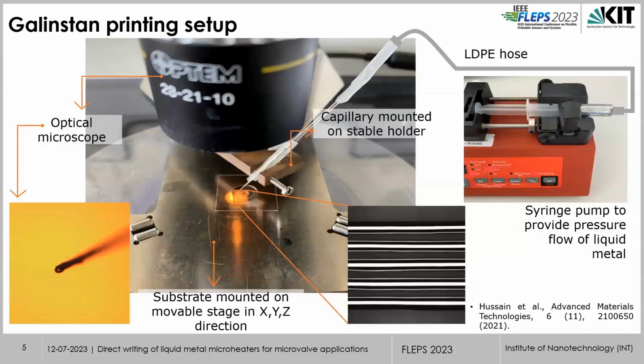This is how the actual setup looks like. This is the glass capillary connected to this syringe pump with the plastic hose. We put pressure here, and the liquid metal comes out of the glass capillary tip here. The stage can go in X, Y, and Z directions, and we can print different widths of lines and everything.